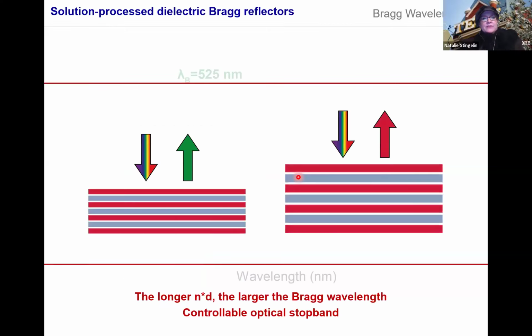So it's important though that we can really change the color of those mirrors. We can manipulate the Bragg wavelength—that's the wavelength that is predominantly reflected. And we can do that, as mentioned before, just by changing actually the thickness of those layers in your stack.